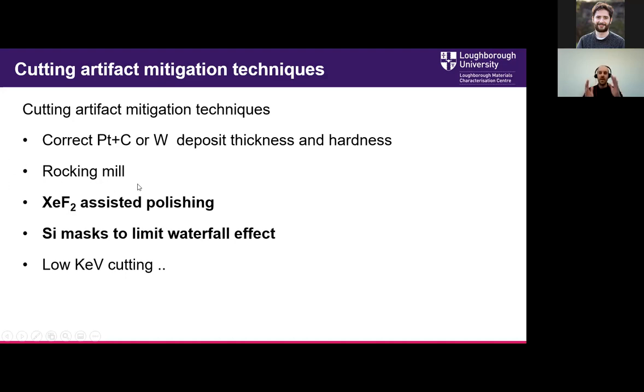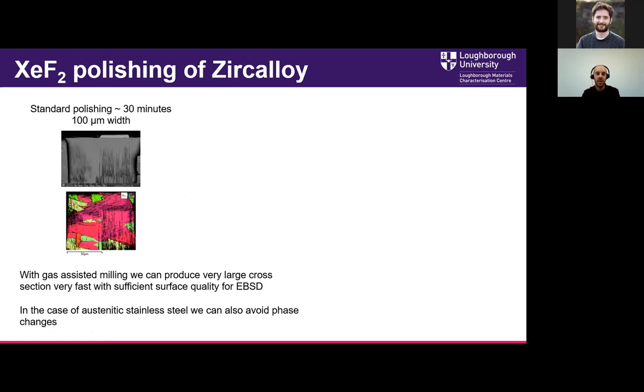Essentially we twist the sample as we polish, and that tries to get rid of some of those curtaining effects. Something we've been exploring at Loughborough is using xenon difluoride assisted polishing and silicon masks to limit the waterfall effect, and also low kV cutting. So I thought we'd touch on the xenon difluoride polishing.